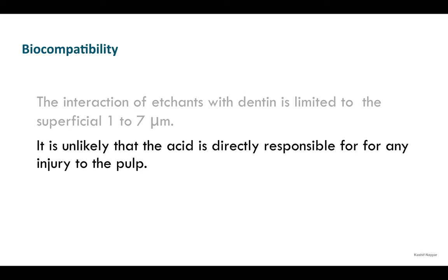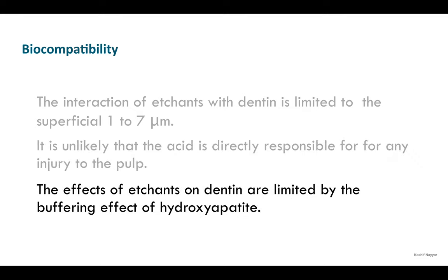It is unlikely that the acid can be directly responsible for any pulpal injury. The effects of etchant on dentine are limited by the buffering effects of hydroxyapatites, which are being leached out and continuously buffering the immediate surface which is in contact with the etchant. So it is prudent that whenever you apply the etchant, you always rigorously scrub, so you may get a more uniform